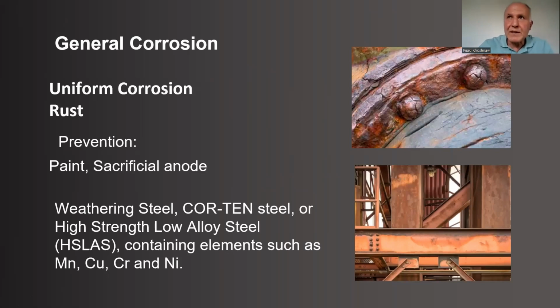Some companies or some countries use this, especially outside the cities, because as we said, the appearance is not that attractive, but it is cheap compared with, for example, cladding with stainless steel, because if it is stainless steel, then the chromium and nickel become much higher than in this type of steel. But it lasts for long, because with time this protective layer becomes stronger and thicker, so it will be protective.